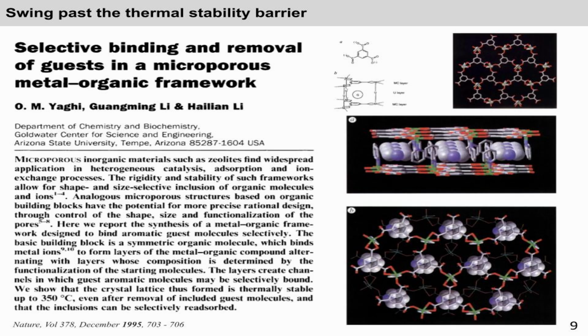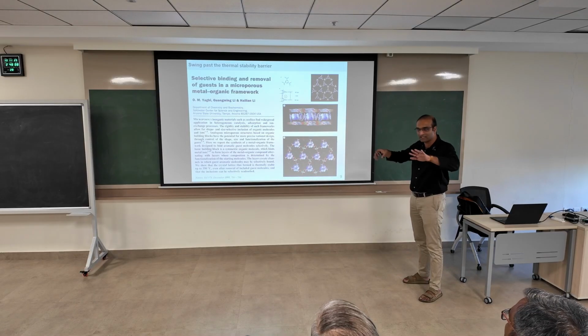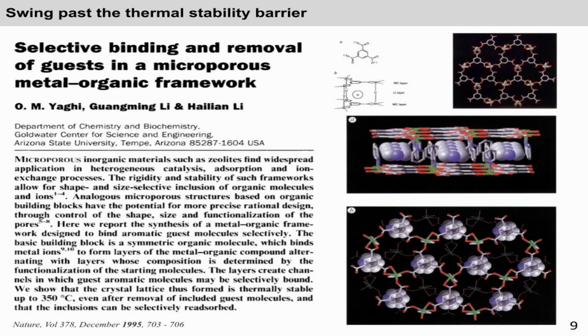So this is the paper that Yaghi published. That is his first instance of actually showing these linkages. Okay, they made this 1,3,5 tricarboxylic acid type of linker. So typically, what happens is you have a linker and you have a metal node. In this particular case, the metal node was, I think, zinc. So you'd form these linkages across. This would be extended across a layer. And then you would have a pyridine molecule holding a secondary layer. Like in between one flat layer like this, you'll have pyridine molecules holding these layers together.